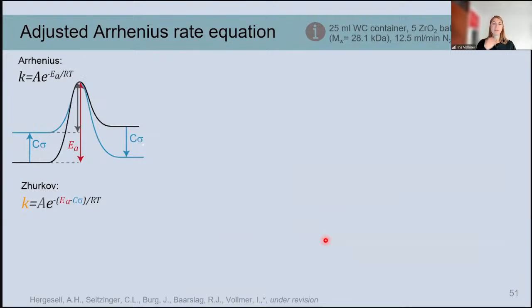And so then in the beginning, I explained this concept of lowering the activation energy barrier by increasing the energy of the initial state by basically stretching the bonds of the polymer. And this is described by what I call the Zhurkov relationship, because there's a paper by Zhurkov where he first describes this, but there are also other papers from other authors that developed something very similar. And with this, you can describe this lowering of the activation energy barrier by this term Cσ. And C is just an empirical constant that I will talk a bit more about later. But σ really relates to the energy of the bonds, or the force that you apply.